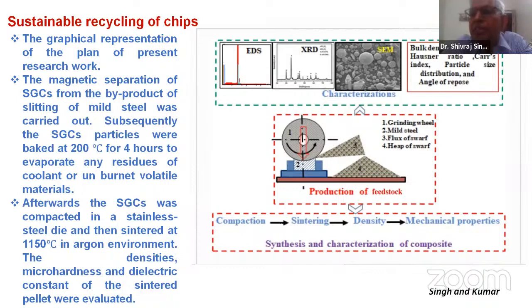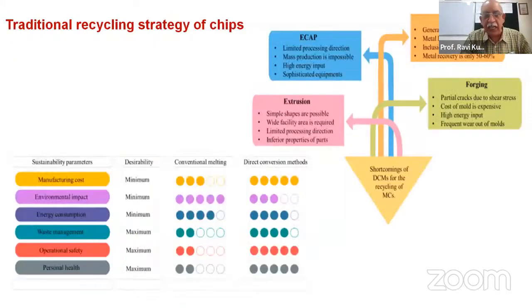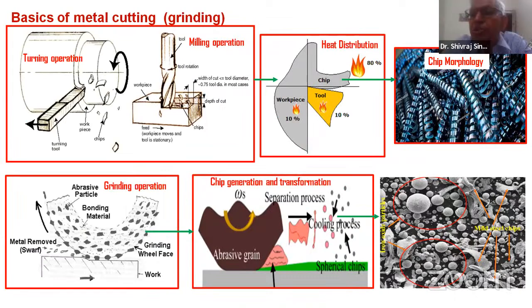We are basically charging this, after drying and dewatering, into an AOD furnace. We are charging it along with the grinder, whether it's a silica grinding wheel or an alumina grinding wheel. So all that sludge also goes along with it, and we are wasting energy on that, because the grinding chips are hardly 10%. Our material removal on centerless grinders is around 8 to 10% of the diameter of the bar. Yes, you are right, that is the process I have mentioned here. So around 2,000 tons of material, we are producing something like 500 to 600 tons of this dust.